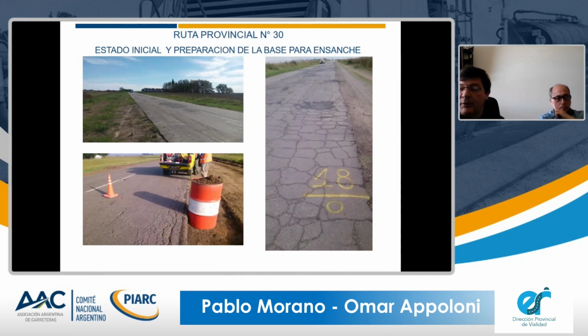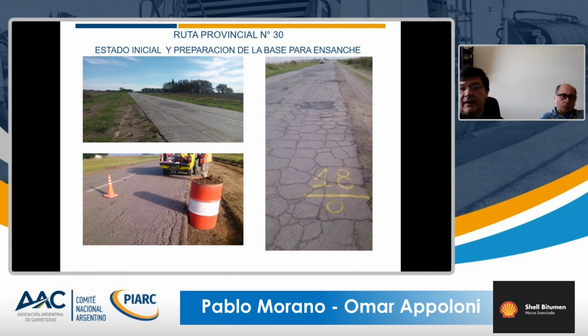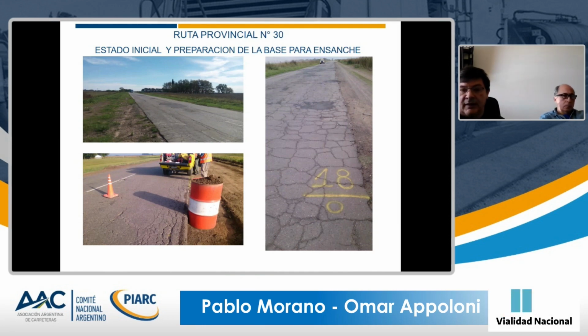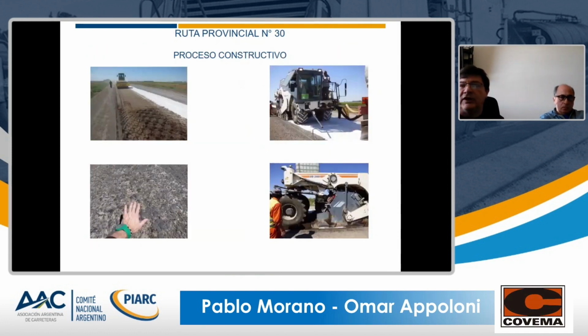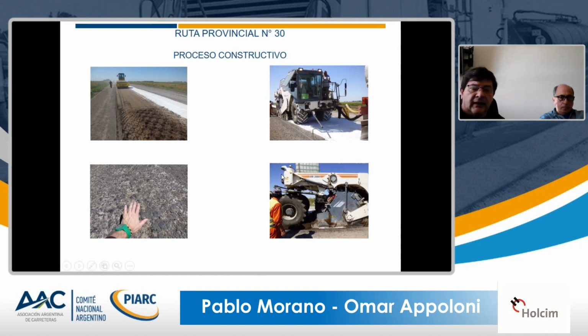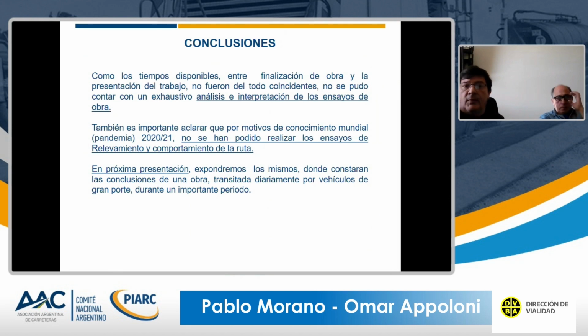This was the status when we found it. This was the condition. It was a problem of the top layer, and on the sides, in order to be able to use the foam, we use cement granular stabilization to do continuous foaming in the 7 meters. Here you have the process when we did foamed asphalt, and then at the bottom you can see the surface of the foamed asphalt, and on top of that we built the other 2 layers.